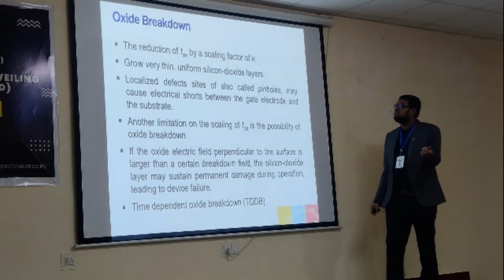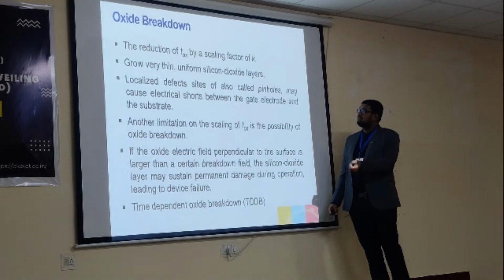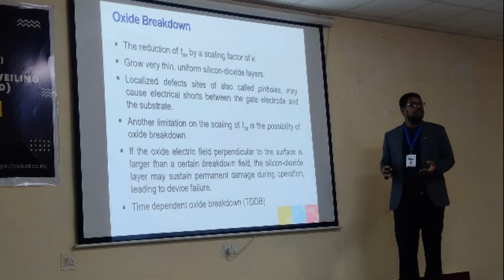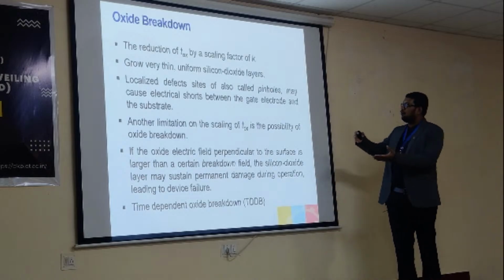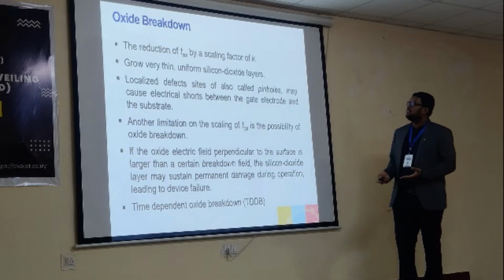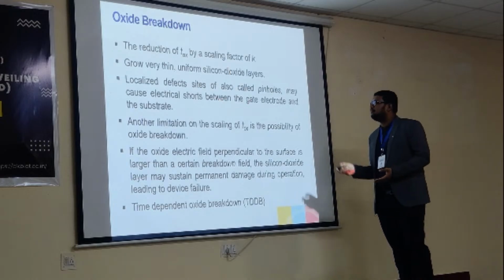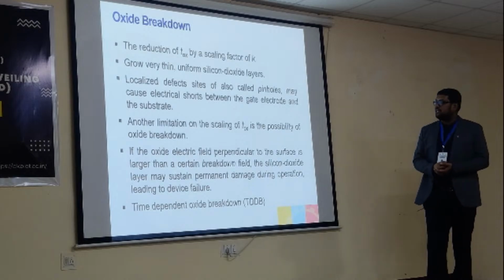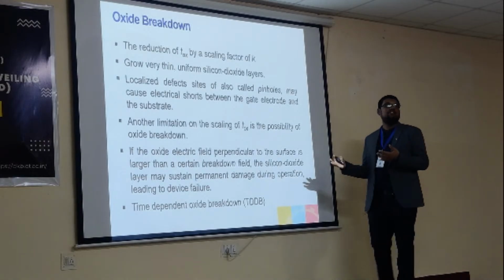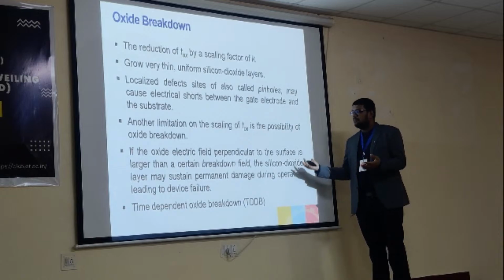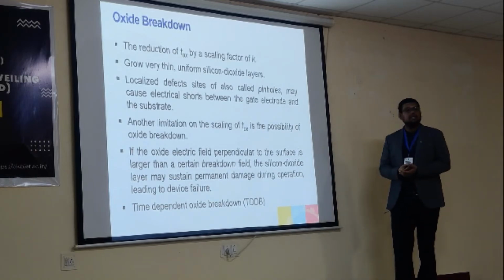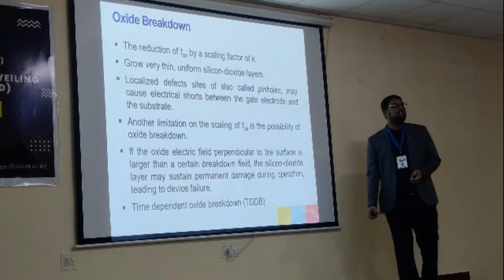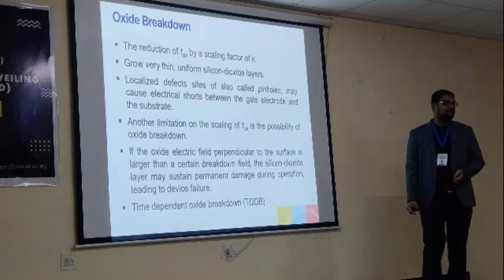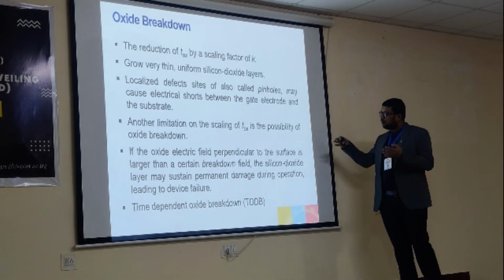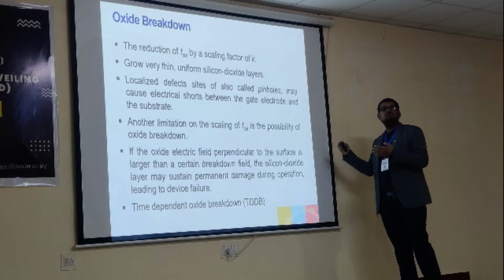Now the oxide thickness is very, very small. But what is the problem? Oxide thickness reduction is not the only way to overcome these short channel effects. If we decrease this oxide thickness, there will be the possibility of oxide breakdown. Oxide breakdown can happen immediately, or it can take lots of time, and after some time the oxide breakdown is possible. Immediate breakdown is possible when the electric field is greater than 6 megavolt per centimeter. That is almost, you can say, a known value.